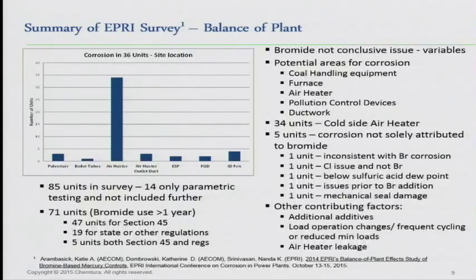There was one issue where they actually analyzed for chloride, but they did not see any bromide at the corrosion points. So their assumption was it wasn't necessarily bromide that was the issue. They had one unit that was operating below the sulfuric acid dew point. That's obviously going to become an issue. And then they had some mechanical corrosion issues in one unit, and there was one unit that was actually seeing corrosion prior to the bromide addition.